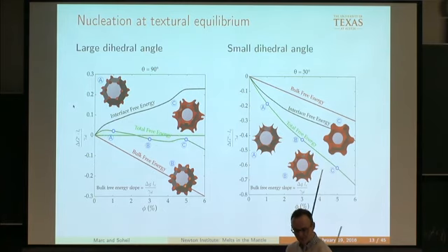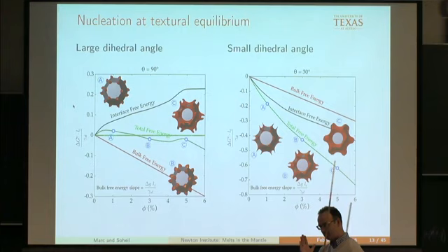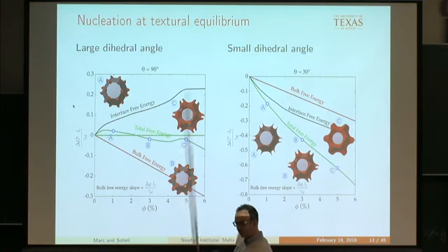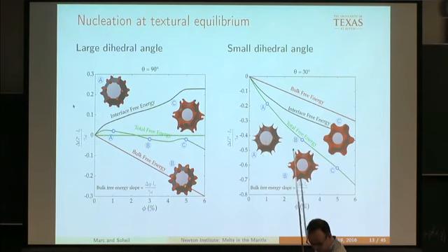And as he was doing this, he needed to calculate all the interfacial stuff, right? And the transition, I think the interfacial energy zero point, for these 3D calculations is at 70 rather than at 60. And 70 is when these grains would essentially be little pyramids with almost flat faces. And maybe that has something to do with it. So this needs more thought, but I think there's clearly interesting things happening here.